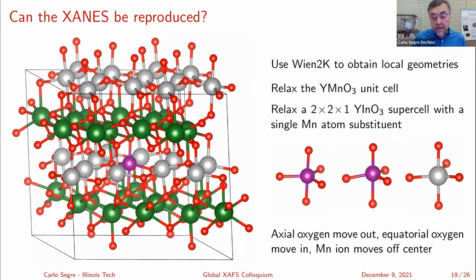But what happens then, in addition, is these oxygens get pulled in tighter. So you can imagine that the volume of the polyhedron or the trigonal bipyramid around the manganese is constant. It gets longer, but it gets thinner. I haven't calculated the volume yet, but that's something I'd like to do just to get an idea of what's going on. So that's saying that the volume that ion surrounds itself with is sort of constant. And again, this is something I've seen before many years ago when I was looking at Vegard's law and how you best plot it.